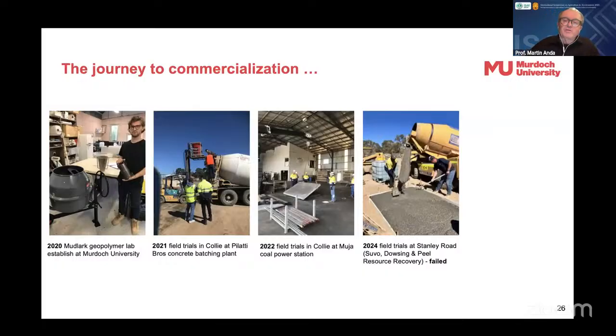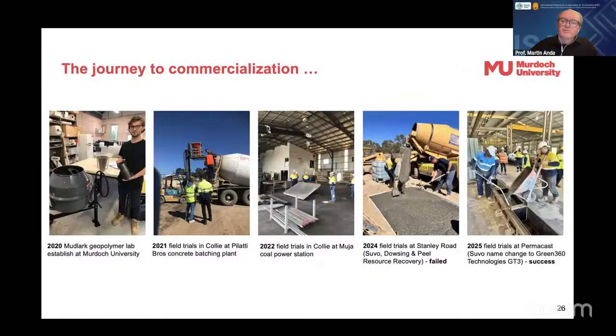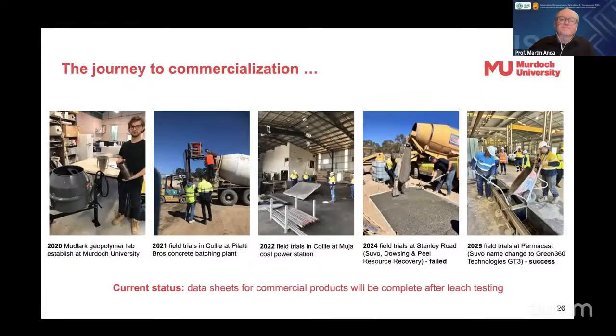and so we've gone back to the drawing board in 2024, and I think we're in a much better place now with the mixed designs that Greg's working with at Permacast, and that's where we're up to now in 2025, that last photograph. So you can see there Greg at work in one of the big warehouses at the Permacast concrete factory, and we're now trialing a number of different mixed designs, including the fly ash, the kaolin, the red mud, the dilithiated beta-spodumene, and we have a number of these underway now, and very soon we should be able to ramp up into commercial scale production with those geopolymer concretes.